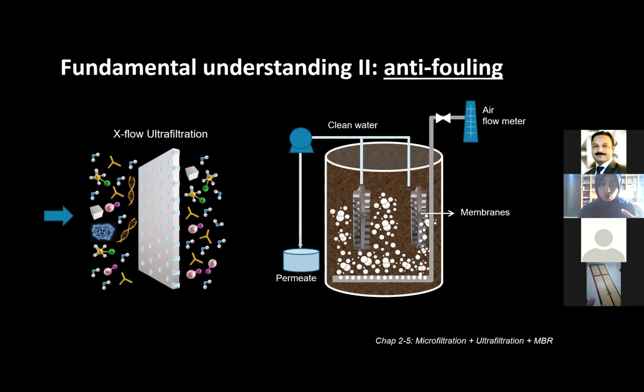This was mainly done by using cross-flow ultrafiltration of the previously mentioned patterned PVDF membranes, in cross-flow filtration using proteins as foulants, and also in membrane bioreactor municipal wastewater.